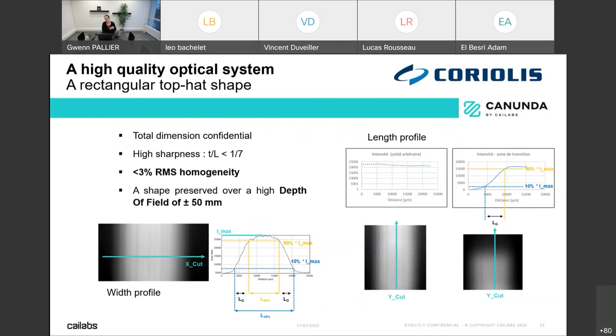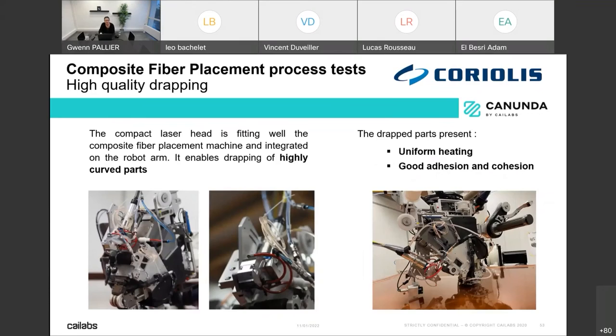We couldn't scan through the whole length of the rectangle because the camera was too small compared to the size of the beam. So we do a scanning over the length, and on the width, we have a scanning of the shape profile. It's extremely homogeneous. It's actually pretty sharp, and we have a huge depth of field, which is very useful to have a robust process. Now let's get to the process results.